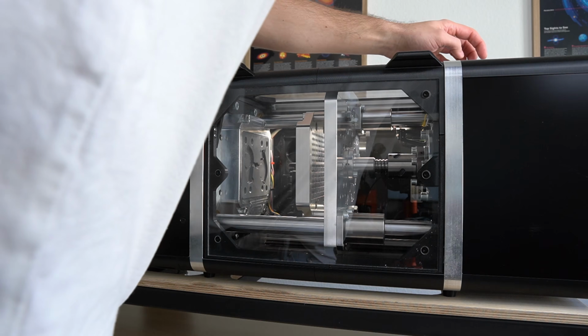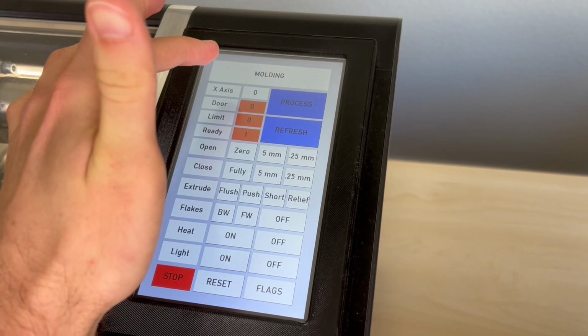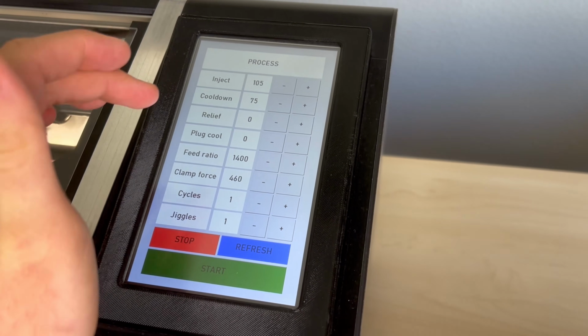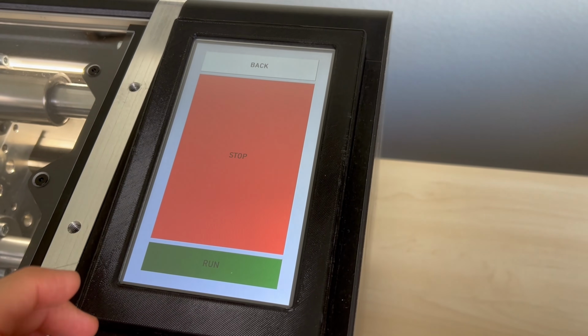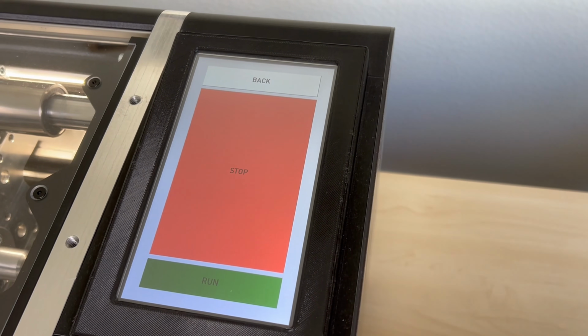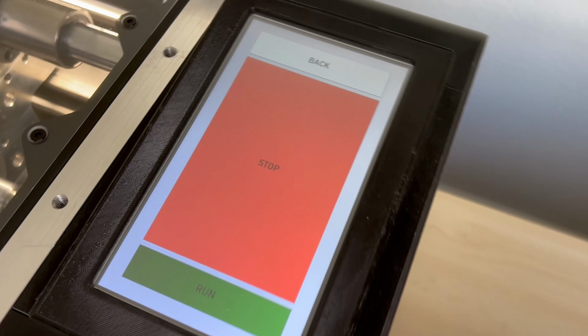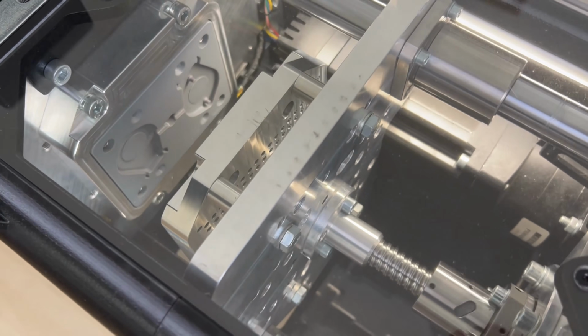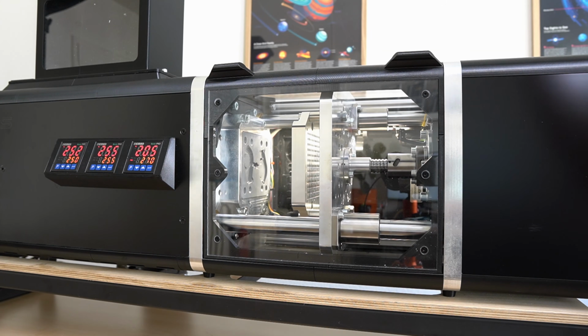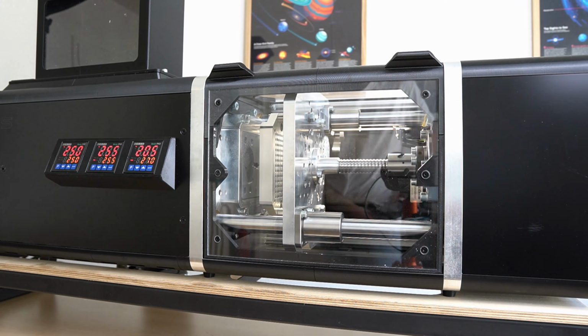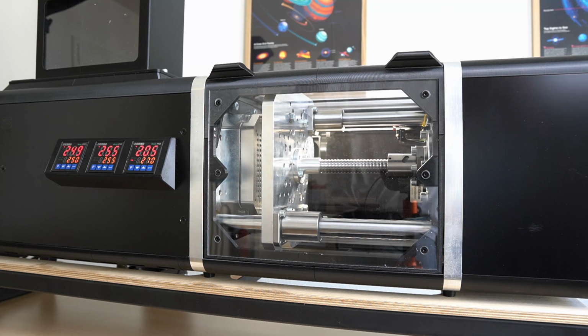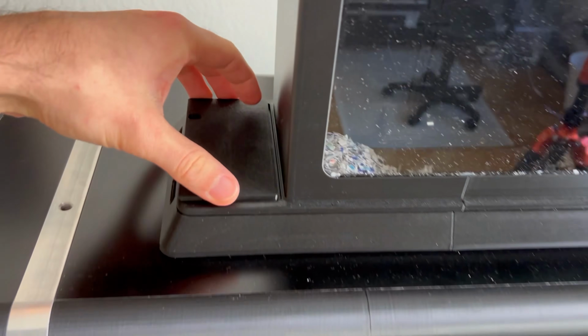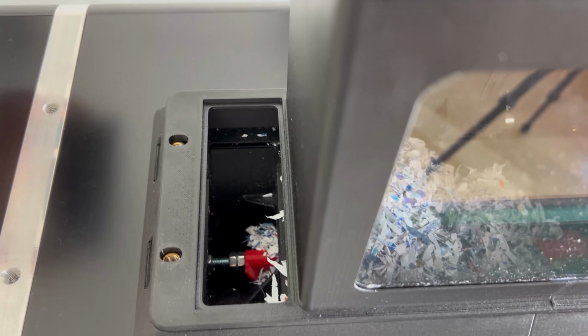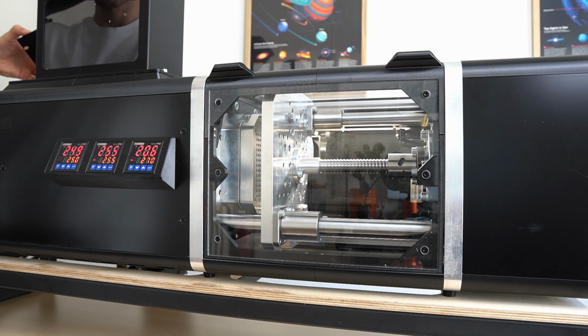Now that the mold is installed, the process can start. In the process page, I can set all values like the injection steps, so basically the amount of grams that are put into the mold, the force so that the clamp mechanism should keep the mold closed, and the cooling times. Each of the produced parts is around 10 grams of polypropylene, and the color they have comes from the material it is made of. These are white and blue cream cups, so the part itself is a light bluish color.